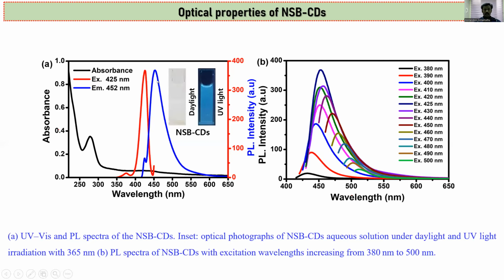Okay, both solutions are colorless, the same as previously, and we can get the blue emission. In the photoluminescence studies, the water-soluble carbon particles show the excitation-dependent feature, the same as explained previously. This also has a maximum wavelength from 380 to 500 nanometer, and we can get a uniform surface defect with the size distribution also at maximum. We can confirm this from the excitation dependence. We can apply the possibility of multiple cell imaging or multicolor imaging.